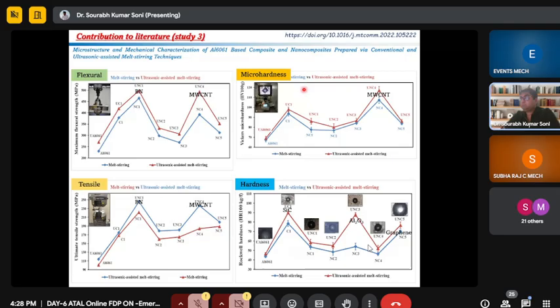So we can relate what is the implication or effect of reinforcement. Here you can see flexural property is almost high in boron nitride and MWCNT, but microhardness is very high in MWCNT, and again tensile stress is very high in BN and MWCNT, and hardness is very high in SiC, Al2O3 and graphene. So there is some deviation. Why is there some deviation?